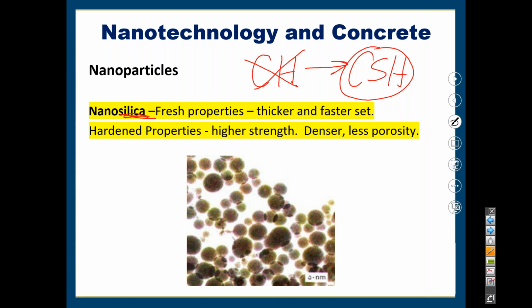But it also has a nucleation effect. And nucleation effect is pretty common among all nanoparticles and other materials, which is it provides a site for hydration to occur. It provides sometimes what they call seeding, where it provides an area for the cement grain as it hydrates to attach to, and the calcium silicate hydrate forms from that point, that seeding or that nucleation site. The more of those you have, the faster the hydration occurs and the more filling of the open pores that you have. So the nucleation effect is the second thing that nanosilica does.